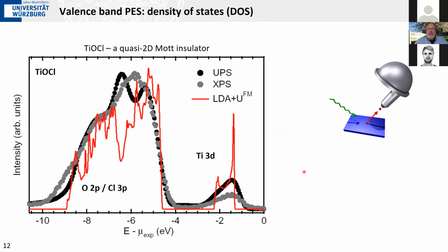And then, of course, we have the valence electrons, and that's particularly important because these are the electrons that are responsible for all the interesting materials properties, conductivity, optical properties, and so forth. And you can, of course, also look at them directly. Here I show you an example of titanium oxychloride, which is a low-dimensional, quasi-two-dimensional Mott insulator. And in this case, it's taken with XPS, which means we take X-rays as excitation source radiation, and a second spectrum that has been measured with ultraviolet light with photoelectrons of 21.2 electron volts.